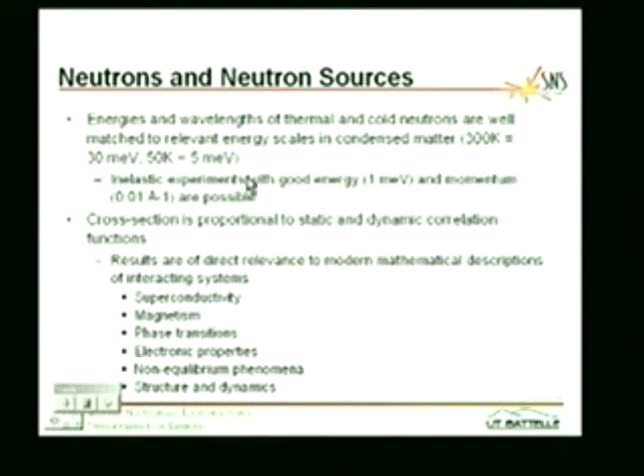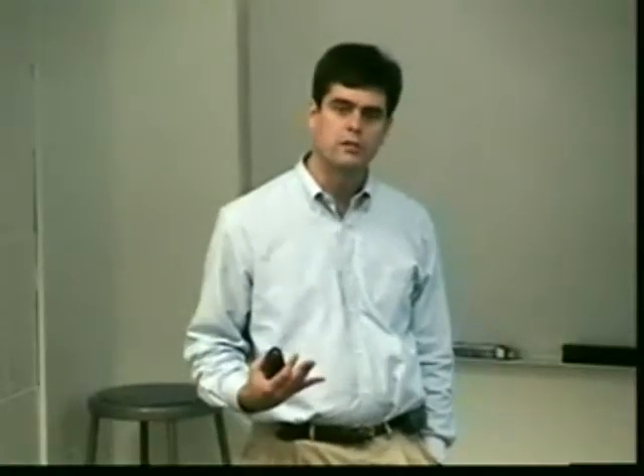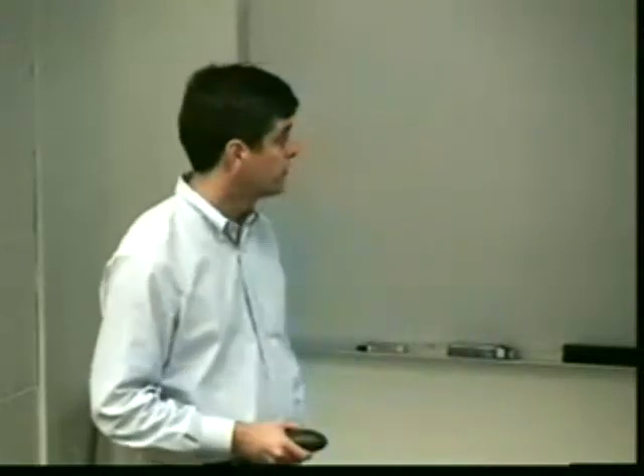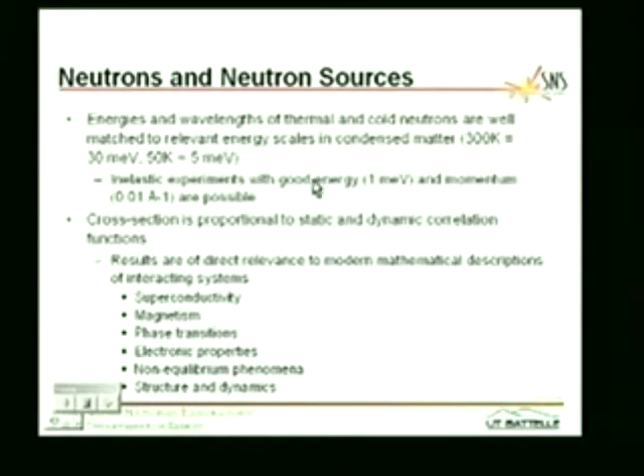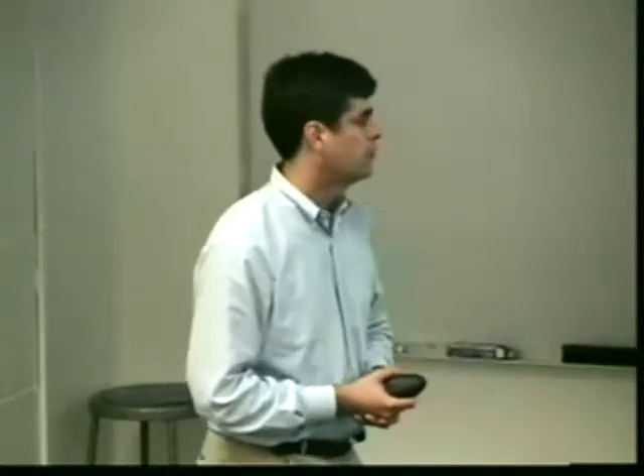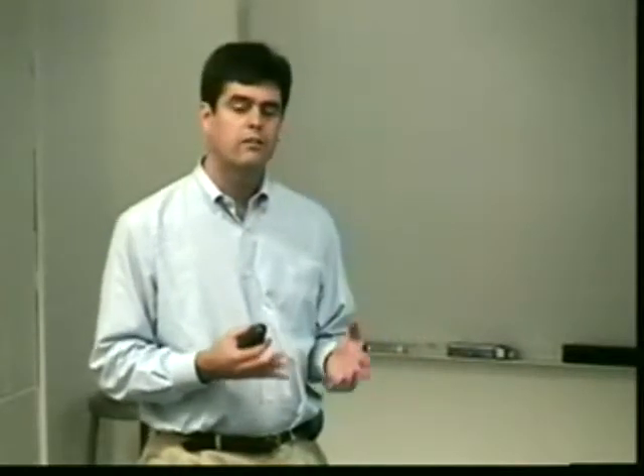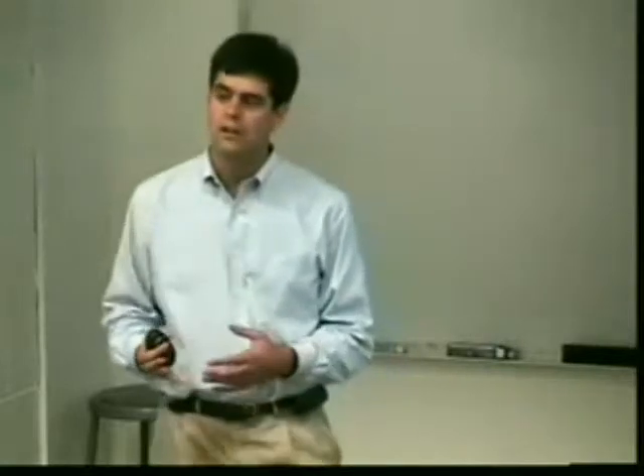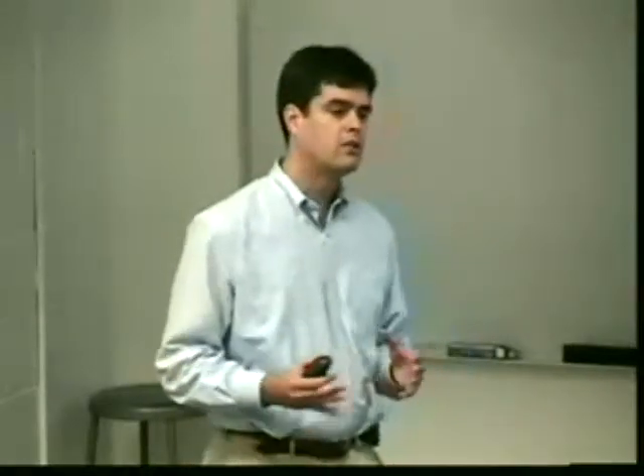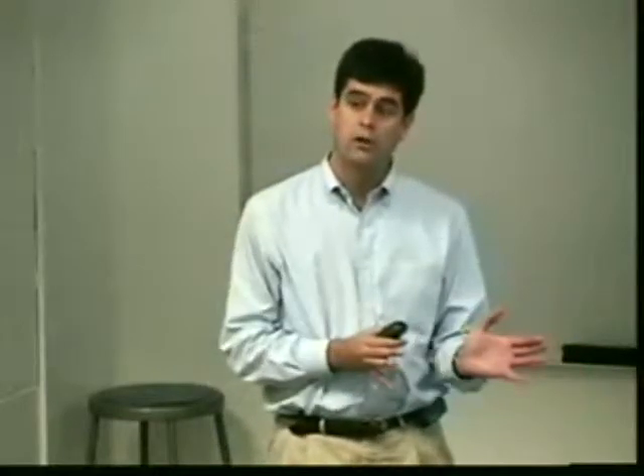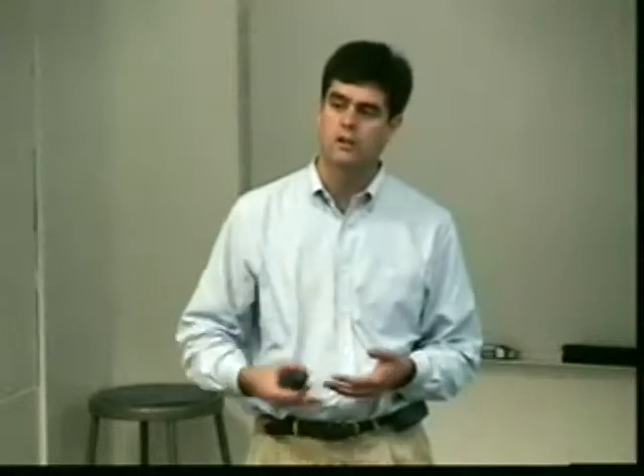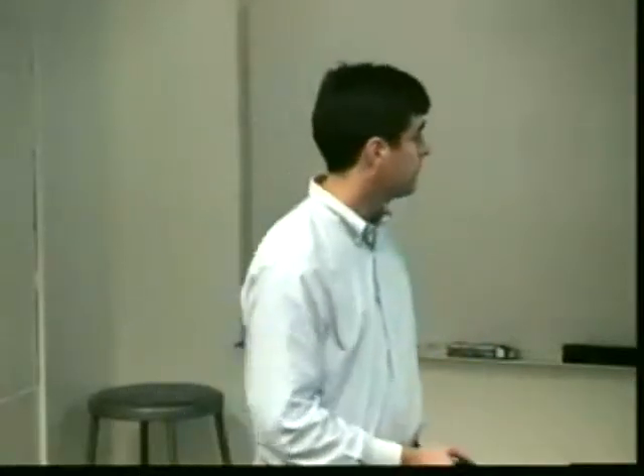Those energies, just like the length scale maps onto the interatomic spacing, the energy scale of neutrons map onto the low-lying vibrational modes in materials that are responsible for things like sound velocity, what we call the phonons and so forth. So it means you can simultaneously resolve in energy and momentum. So you have access to the whole sort of four-dimensional space-time world that we live in. And certainly if you're interested in things like phase transitions, then excitations who have energies of order kT are important for driving phase transitions. So in addition to the structural utility of scattering neutrons, you also have this ability to do dynamics and look at the thermodynamically relevant excitations.